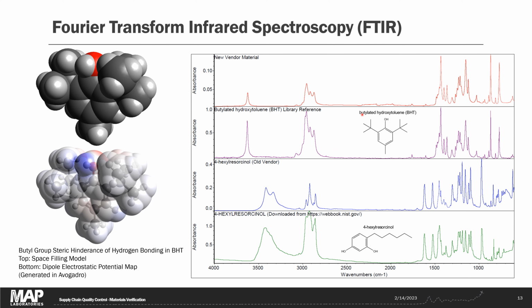This is obviously a lot more complex than the CO2. There's a lot more peaks, but there's a couple interesting areas in here where we can look. One is that there's a lot more end groups on these butyl compounds relative to hexylresorcinol here. We only have one CH3 group on hexylresorcinol. We have 1, 2, 3, 4, 5, 6, 7 on BHT. And that results in the CH stretching region looking a little bit different. We have this CH3 stretching peak that's much higher relative to the CH2 of hexylresorcinol. So we have the difference here in the CH stretching region.